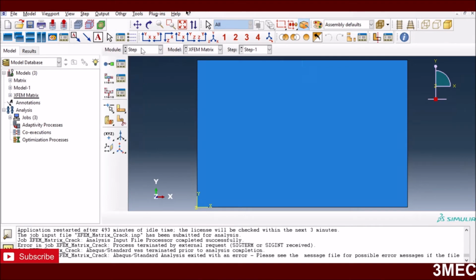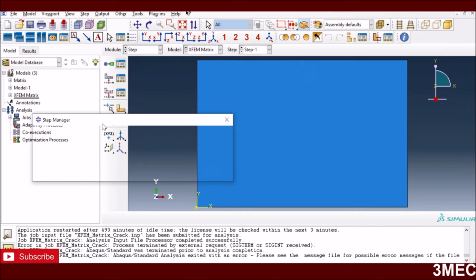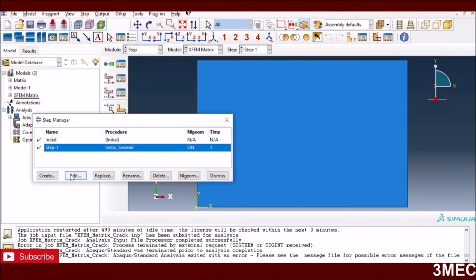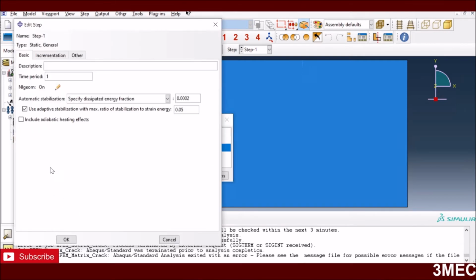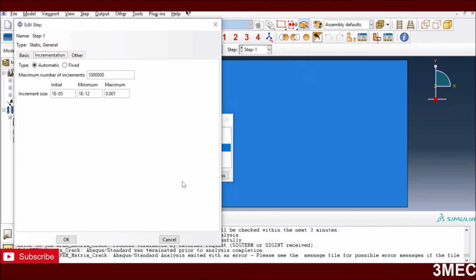Then I go to the step module, and this is where you have to be careful. So first thing is I am using a static general step. You can just press the create button and this window will come up. So I have turned on the automatic stabilization option, because as soon as your material starts to fail, you will come across negative stiffnesses and your solver will struggle to converge. So that's one thing you have to do.